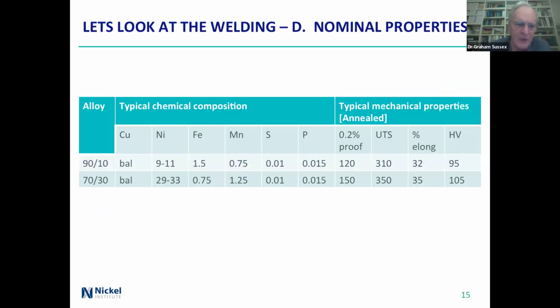The nominal properties of the two - the 90-10, well, 10-ish nickel, 1.5 iron, you need a bit. The manganese is a deoxidizer, the sulfur is a deoxidizer, but there's nothing much there. And the phosphorus, you really can't get much lower because, hey, it's just there in the background.